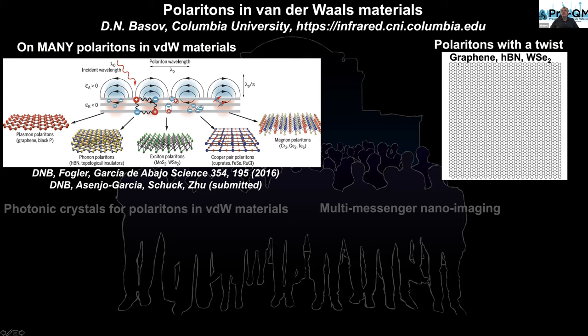Many of these materials can be fabricated or exfoliated in the form of a single atomic monolayer. So if you put one monolayer on top of the other monolayer, if you are in perfect registry, you actually don't see anything. But if you rotate one layer with respect to the other, then you start seeing periodic superlattices with periodicity determined by the twist angle between the two layers. So a minor rotation changes in a major way all of the properties of these heterostructures: excitonic behavior, polaritonic behavior, electronic transport, heat transport even, and the light transport in the form of plasma polaritons that I will discuss in more detail.